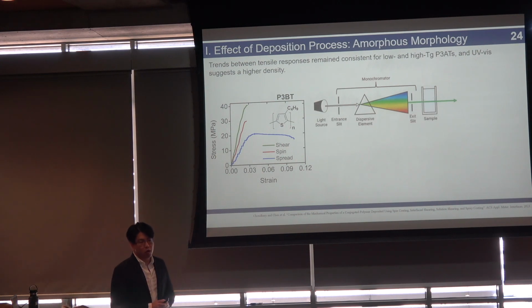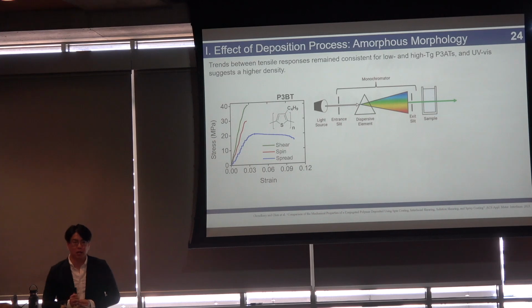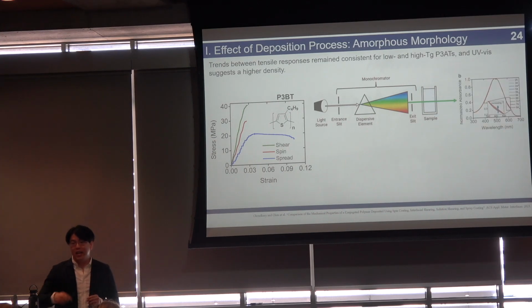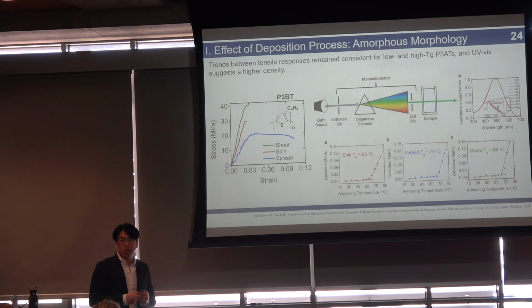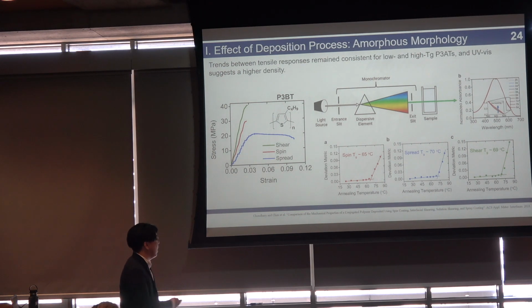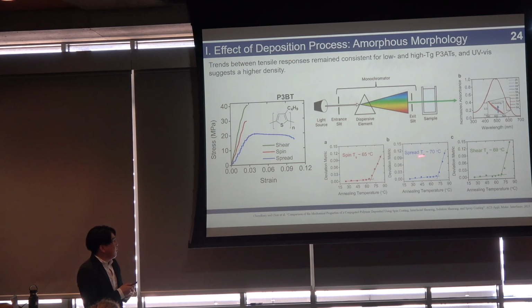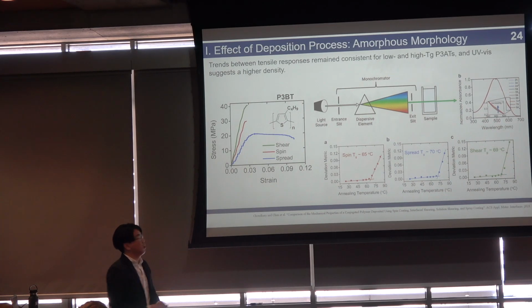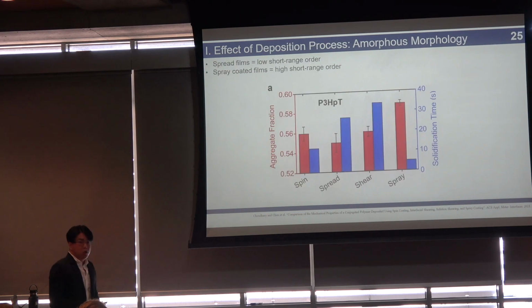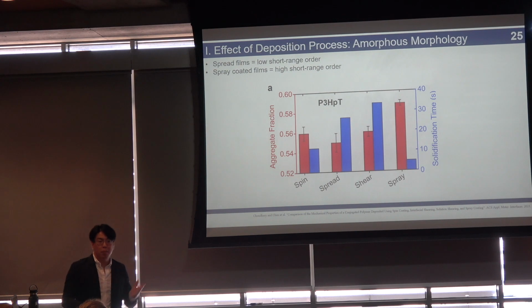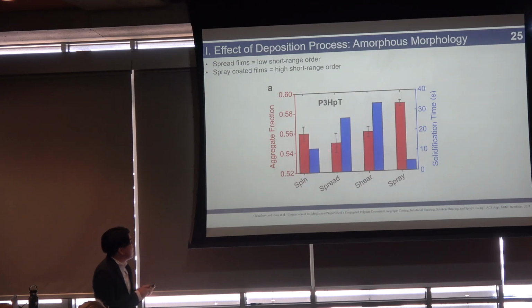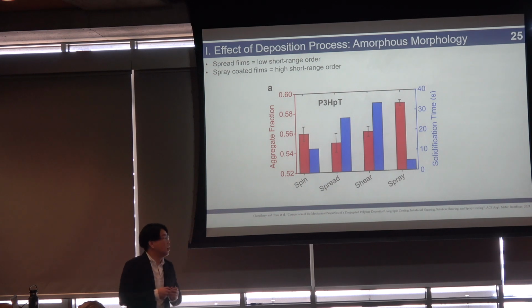So to look at the amorphous morphology, we can use UV-vis. We can shine light through this and look at the absorbance spectrum. And by repeatedly heating and cooling our films, we can approximate the glass transition temperature by the thermal transition of the aggregates. And we see that spread films and sheared films both have a higher glass transition than spin-coated films, which suggests a lower free volume and a higher density. Using UV-vis, we can also extract the aggregation, so basically how ordered the amorphous domains are. And we see that spread films have very, very low short-range order, while spray-coated films actually, surprisingly, have very high short-range order.